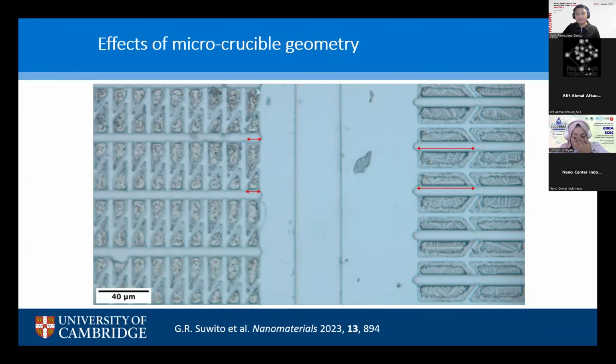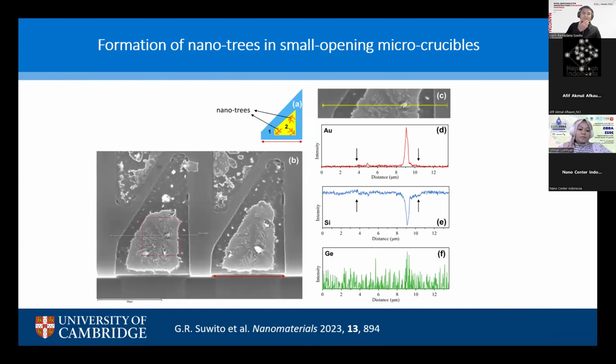So effectively, the opening is much larger on the right side sample. And you can see, even on the optical microscope, a difference between these two features. This is interesting because these two arrays of nanostructures are located close to one another, maybe 120 micrometers, which is quite close, and on the very same substrate. Of course, optical microscope is not enough, so we need to do further micro and nanoscale characterization.